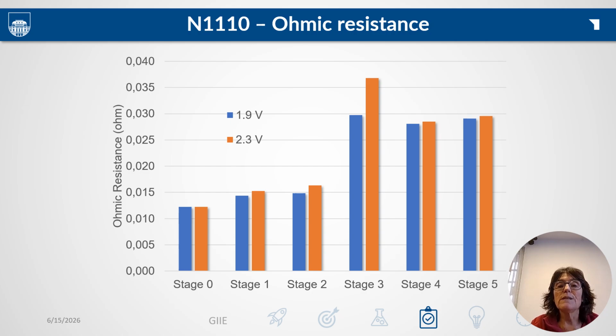The ohmic resistance is controlled by the protonic conductivity of the membrane and the contact resistance between catalyst, binder, and membrane. The fact that it doesn't recover even with acid treatment indicates that the Nafion 1110 membrane itself has suffered structural degradation. This is the fingerprint of irreversible damage to the membrane itself.